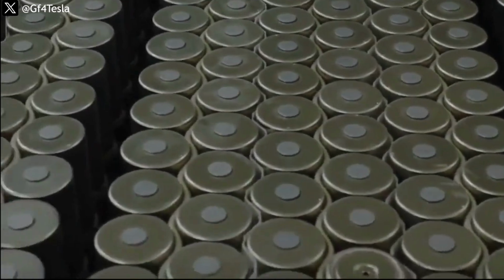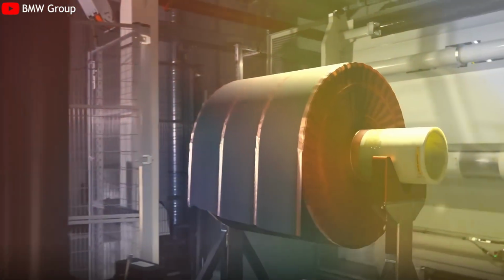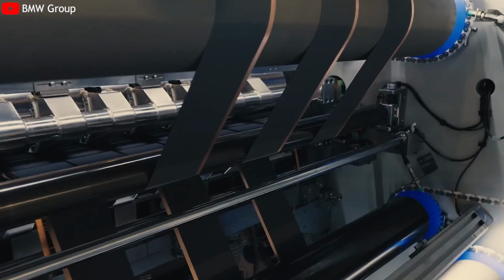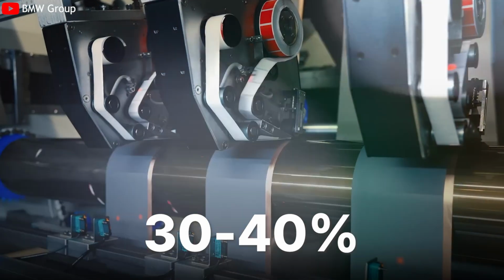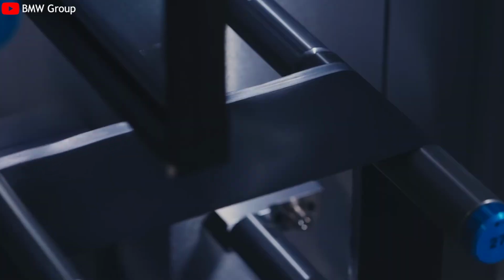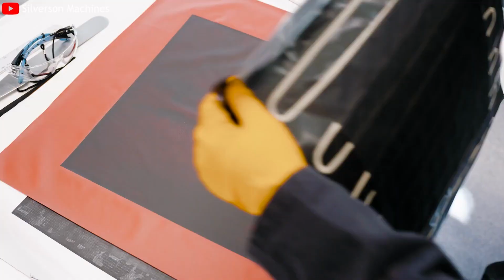battery cells per year. In traditional lithium-ion manufacturing, electrode coating and solvent drying alone account for roughly 30 to 40% of total factory energy consumption. Dry electrodes eliminate N-methyl-2-pyrrolidone solvent entirely, along with the massive drying ovens that can stretch over 80 meters per line.